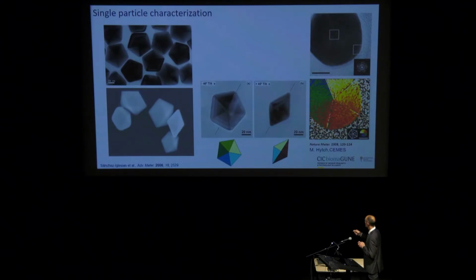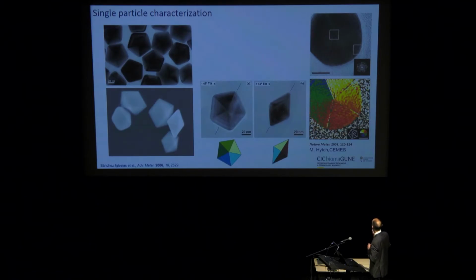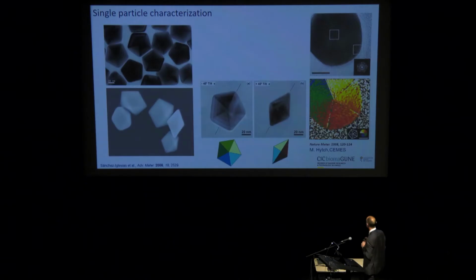And they are very tricky because they are made of 5 tetrahedra of FCC crystal. If you put together 5 tetrahedra, the angles don't match the 360 degrees that you need to close the decahedron. So what Martin did was first to do high-resolution TEM, and then he measured with electron holography the stress in each of the single crystals that form the five single crystals coming together. With this, it's actually easier to understand how the thermodynamics works to stabilize this type of particles.